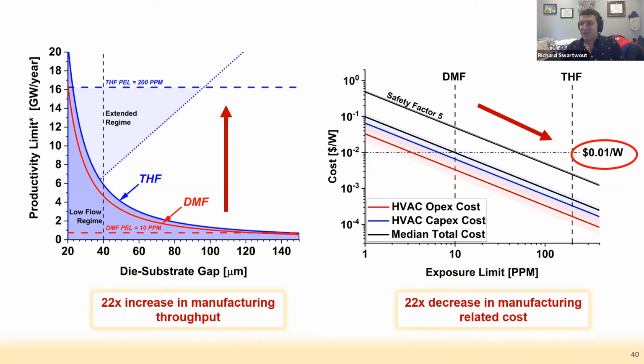So if you take nothing else away from this, either the math or anything else, there's a good rule of thumb you should follow in this field: you shouldn't be using any solvents lower than about 100 parts per million permissible exposure limit. It's just going to be uneconomic and it can't actually scale.